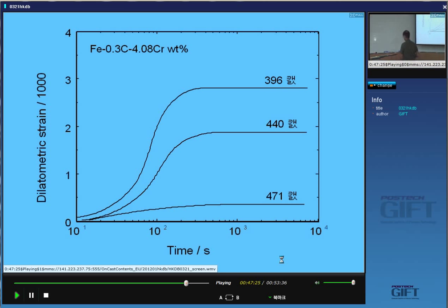So this is called the incomplete reaction phenomenon, because here there's plenty of driving force for austenite to transform to bainite, but not for austenite to transform to ferrite without a composition change. So we've reached a limiting fraction of bainite, even though we are well below the equilibrium temperature. That's why it's called incomplete reaction. It hasn't reached equilibrium, and it won't as long as the mechanism is bainite.